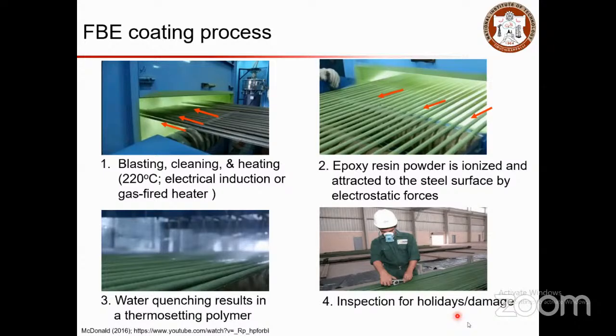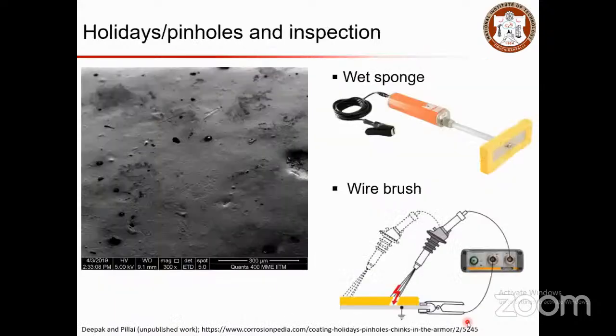For a certain length, you have some allowable limit of holidays or damage, which is less than 1.1% or so. If it is more, then that is going to accelerate the corrosion in a negative way. So here is the microscopic image of the coated surface. You can see small pinholes. These are called the damages or the holidays.